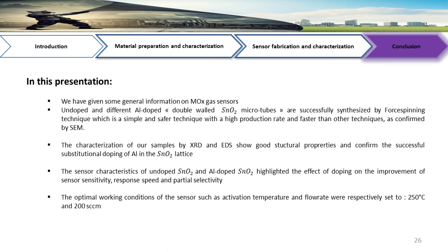Finally, in this presentation, we have given some general information on metal oxide gas sensors. Undoped and different aluminum doped tin oxide microtubes were successfully synthesized by the force spinning technique, which is a simple and safer technique with a high production rate and faster than other techniques, as confirmed by scanning electron microscopy. The characterization of our samples by X-ray diffraction and EDS show good structural properties and confirm the successful substitutional doping of aluminum in the tin oxide lattice.